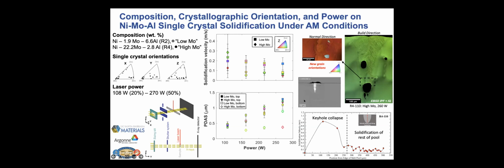When we have a keyholing regime, like that shown here on the right in our radiography, we end up with a keyhole collapse. We form a void that's present there. When that keyhole collapses, we experience a very high velocity at that point in time. If we zoom in and do post-mortem characterization, we can see at the location where that keyhole collapses, where the high velocity is experienced, that we have new grain orientations that form. This suggests that these high velocities trigger the columnar to equiax transition and the formation of these new grain orientations. So we not only can understand the way microstructure develops, we can understand the formation of defects as well from these kinds of experiments.